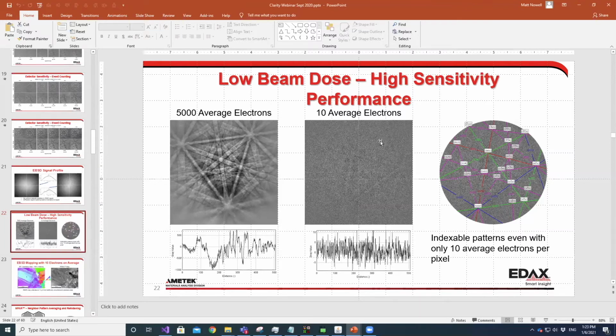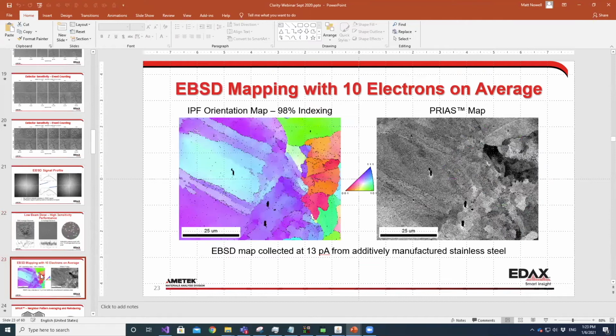But we can run down to where we're running with 10 electrons on average. So, not a lot of signal, but even in this pattern, you can see a diffraction signal. And when we look at this, we can actually run maps with that sort of a signal level. So this is with nominally 10 picoamps of beam current, and can still get very high success rates because we can resolve the patterns because there's essentially zero noise in the signal. And so that's what we're able to do.